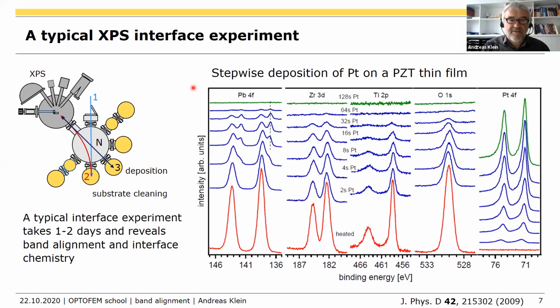Okay, so that's just an example. This is what happens when you deposit platinum on a PZT, lead zirconate titanate thin film. The red one is the original spectrum, the clean PZT substrate. There is no platinum. There is an oxygen, there is a titanium, there's a zirconium, and there is the lead peak. These 2 peaks are always there. This is the spin orbit splitting of these levels. The oxygen 1s doesn't have the spin orbit splitting.